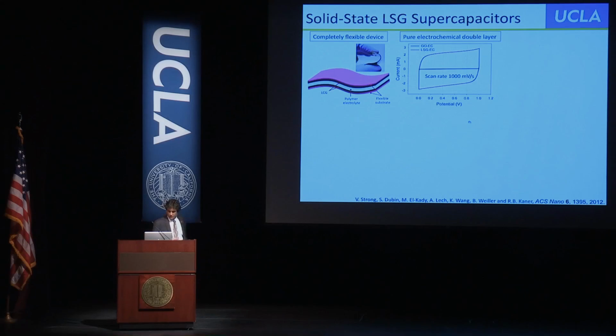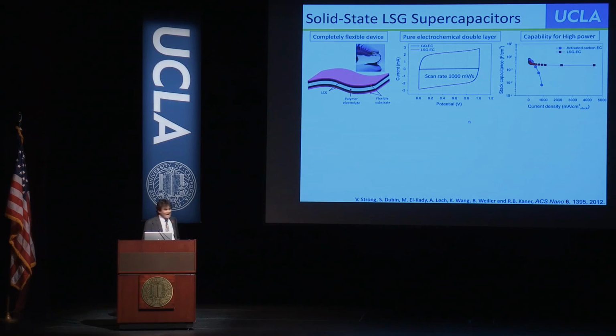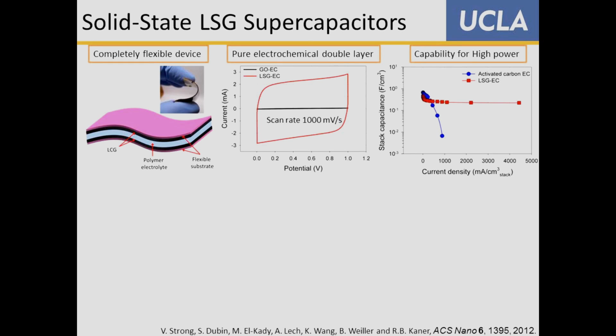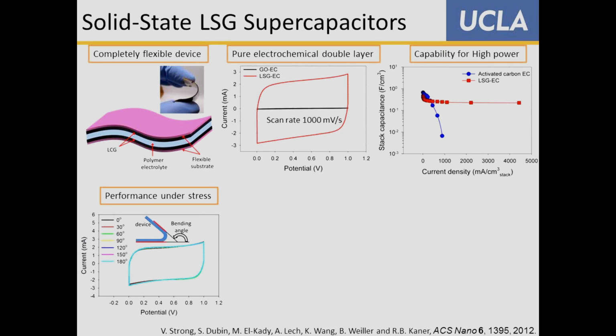And this is called a cyclic voltammetry. And in theory, if you get a rectangular wave, that would be a perfect result. And this is as close as you'll probably ever see to a rectangular wave. When we compare this to commercial devices based on activated carbon, as you drive an activated carbon device faster and faster, it falls off. Our material still keeps performing. And this is up at 4,000 milliamps per cubic centimeter, very high current.